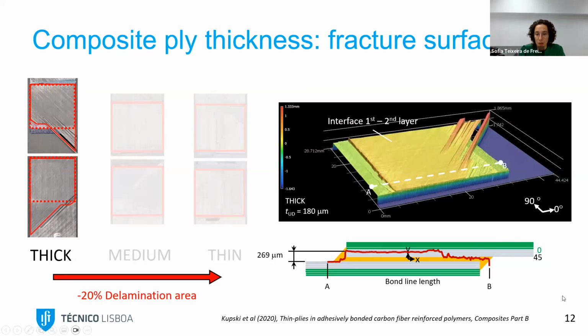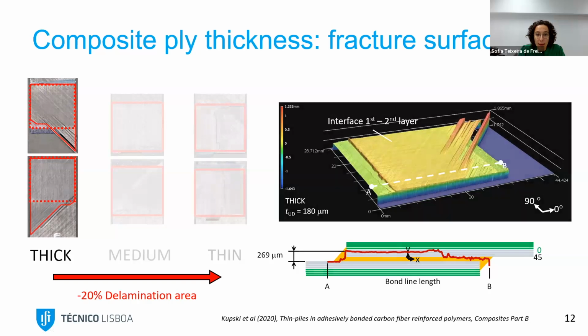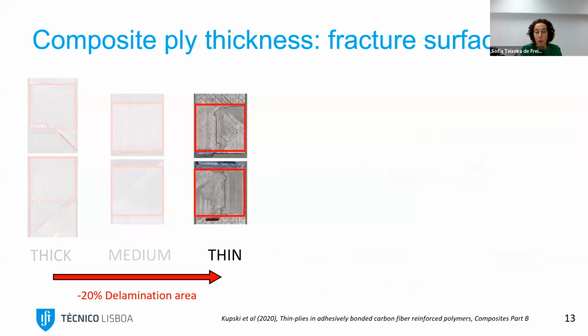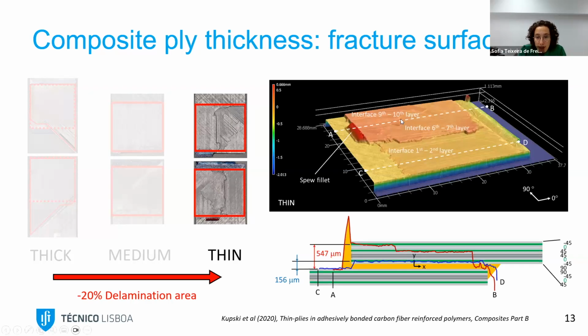So this is a cross section of the specimen. And when we make the same exercise, but now for the thin, we see that we have a quite different fracture surface. So the crack traveled between the interface 9 and 10, 6 and 7, first and second. So there were a lot of steps within the fracture surface that the crack traveled during the damage scenario. So this was quite different from the previous one.